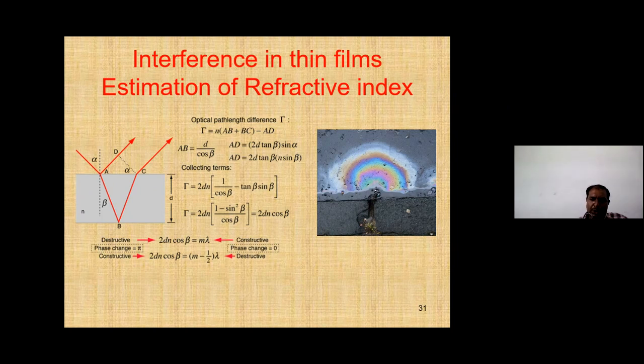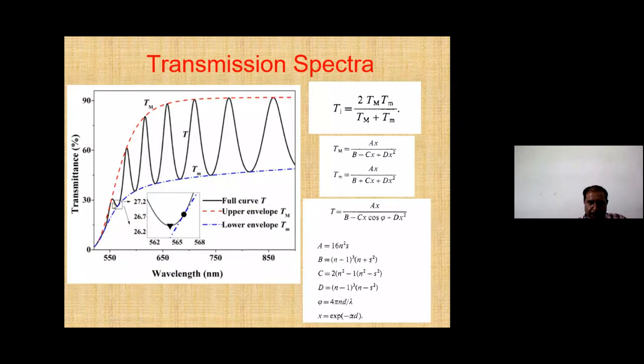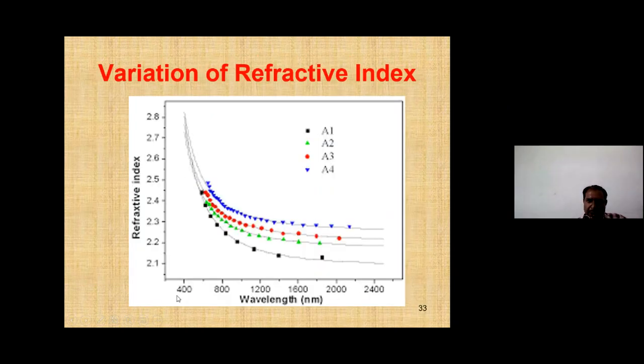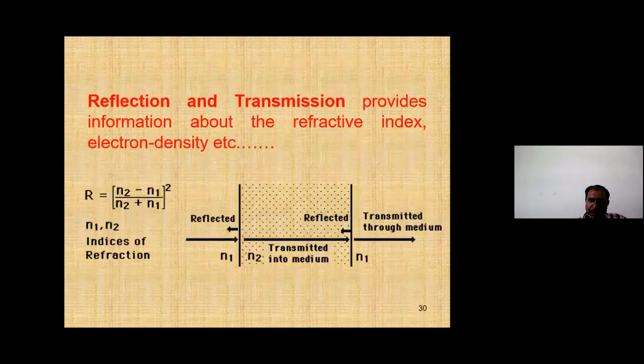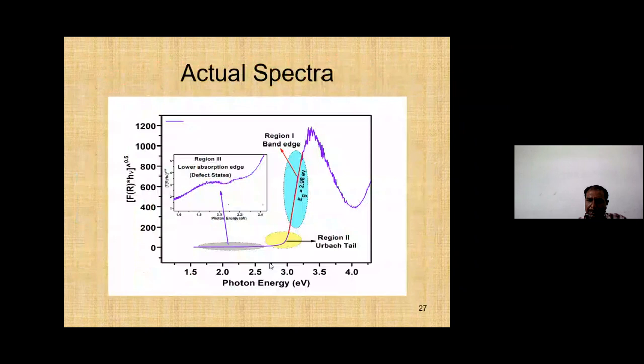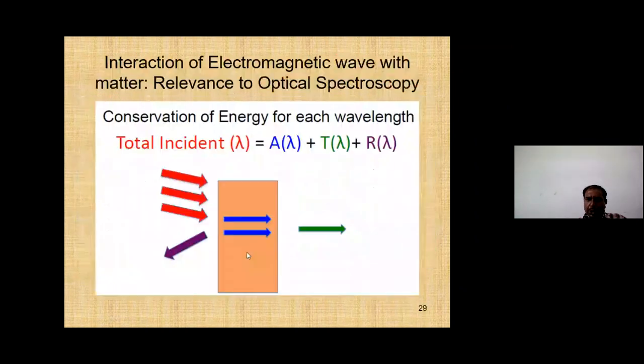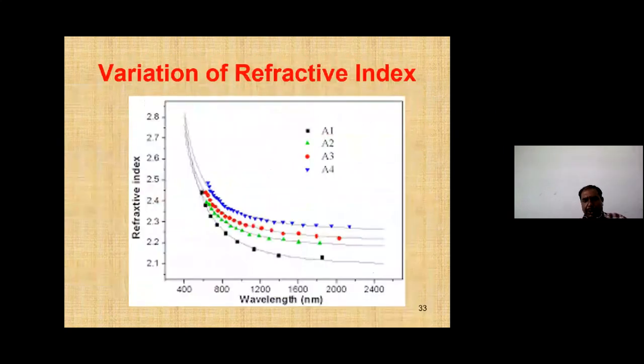If you perform the transmission or reflection experiment on a thin film sample having a substrate which is optically transparent, then you can get such an interference pattern, the constructive and destructive pattern, in the transmission or reflection spectra. From this data you can estimate the refractive index as a function of energy for a given sample. So we can find out not only the band gap, electronic disorder or presence of defects, you can also estimate a very important optical parameter, the refractive index of a sample.